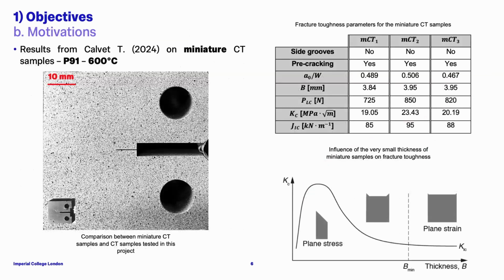The motivation for my project: my work follows on from what a former PhD student did at Imperial College. He did some fracture toughness tests on really small CT samples made of P91 steel at 600 degrees. And he found quite low JIC values. I plotted the evolution of the toughness as a function of the thickness of the sample. And what is worth remembering is that the thinner the material, the higher the toughness, and the thicker the material, the lower the toughness, with plane stress conditions for thin materials and plane strain conditions for thick materials.